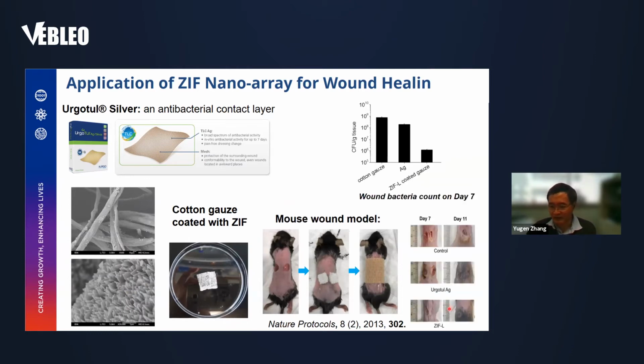And actually, you can see from here, after like day 11, the wound healing performance for our materials is at least comparable with the commercial one. And from this bacterial counting, you can see our materials are even better, with much less bacteria as compared to the commercial one. And yet our materials are much safer and biocompatible as compared to the commercial one.